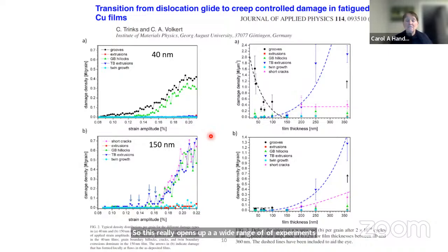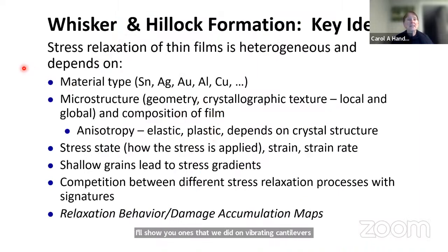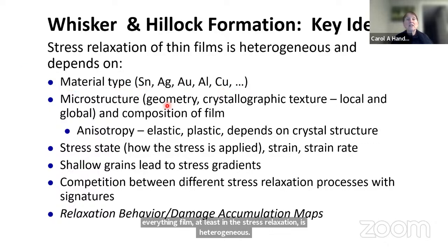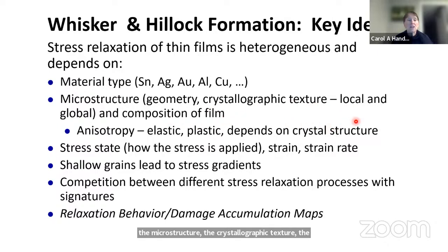So taking inspiration from this, the last set of experiments I'll show you were ones that we did on vibrating cantilevers for tin. These are some of the key ideas: that almost every thin film, at least metal thin film, has heterogeneous stress relaxation. It depends on the material, the microstructure, the crystallographic texture, the composition of the film, how anisotropic it is, and what the base microstructure is. It depends on the stress state and the strain rates. As you know, when you do normal stress-strain curves, the strain rate matters and the total strain matters. So these are all important factors.